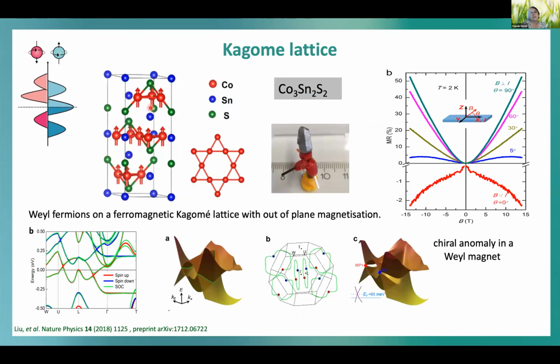So we chose cobalt 3 tin 2 sulfide 2 here, and I chose this also as an example because it has a very nice kagome lattice, and kagome lattices have super interesting band structures. The compound has a half metallic ferromagnetic band structure, and the spins are out of plane magnetized. So if I magnetize them once, they stay magnetized because they are hard magnetic. So it's even possible to measure and maybe magnetize crystals in ARPES. So the first thing we did was really to measure the chiral anomaly, and this you see here.